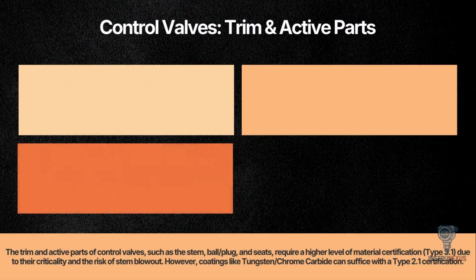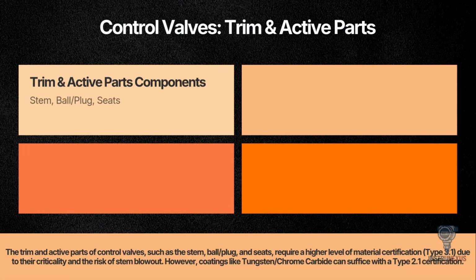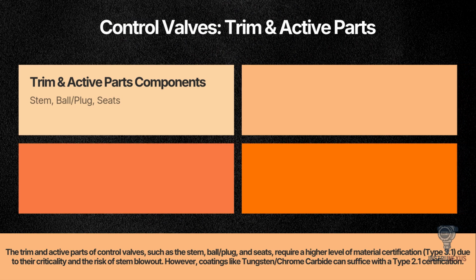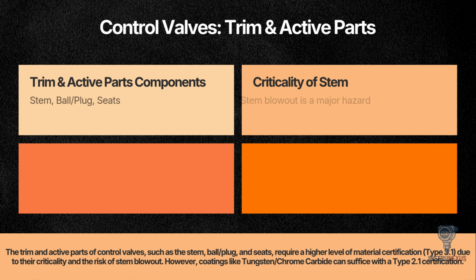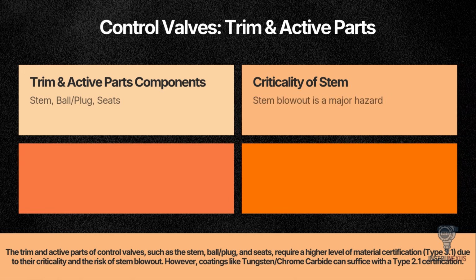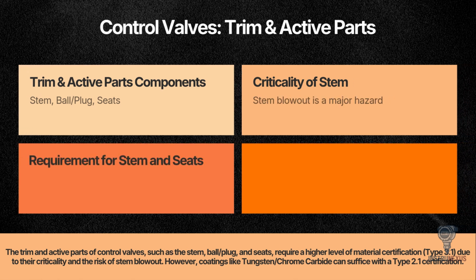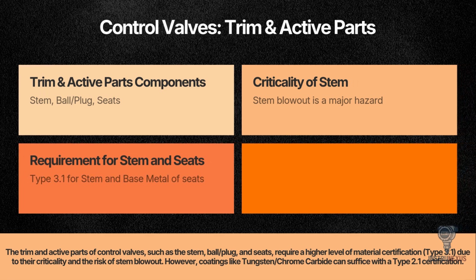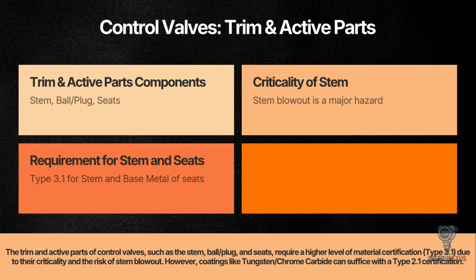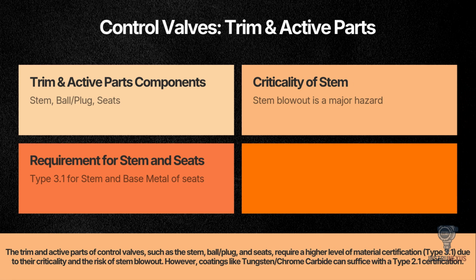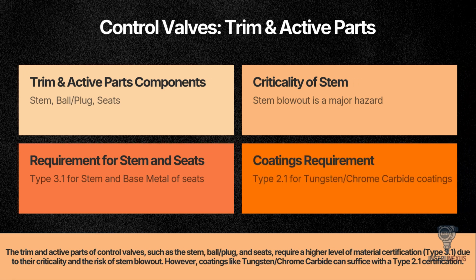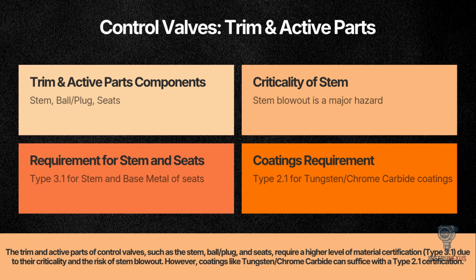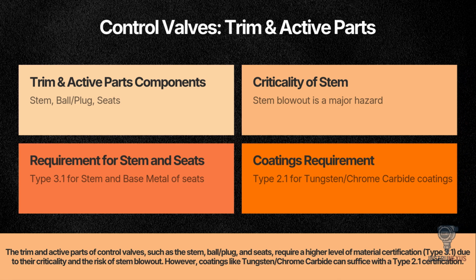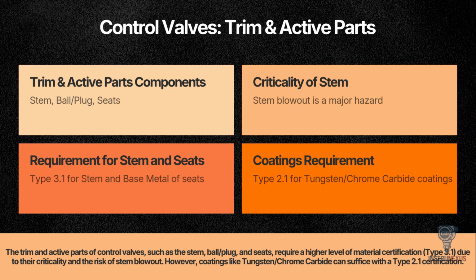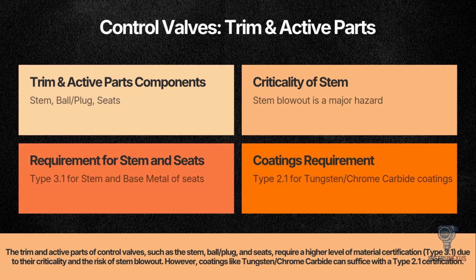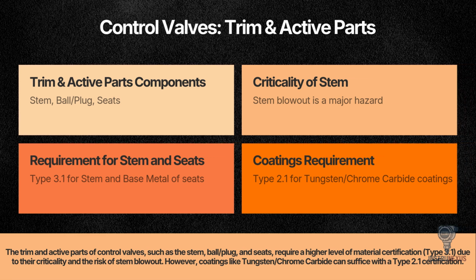Inside the valve, we have the trim and active parts. This includes the stem, ball or plug, and seats. The stem is a critical component. A stem blowout is a major hazard. Therefore, we require a higher level of material certification, Type 3.1, for the stem and the base metal of the seats. However, there is an exception for coatings. Coatings like tungsten or chrome carbide, which are applied for wear resistance, can suffice with a Type 2.1 certification. We need to verify the base metal strictly, but the coating application is treated as a process compliance.